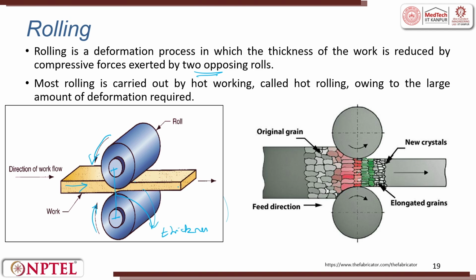The same thing can also be done multiple times, so that in each operation, you try to reduce the thickness by a certain delta x. You can't get from 1 millimeter to 0.1 millimeter in one shot, because then it undergoes strain hardening, and the material feeding will not happen properly. So, what we do is we do step by step.